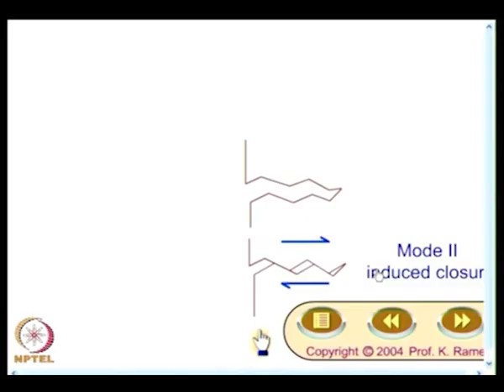So, what you will have to keep in mind is crack closure is an accepted phenomenon, though it was not initially accepted. Later people have recognized its role, and many other mechanisms also people have observed and categorized. In all those cases you should have a methodology to find out delta K effective. So, you have to perform more tests and look at the literature and find out how to get the delta K effective. Only then you will be able to use the crack closure model for finding out the dA by dN.